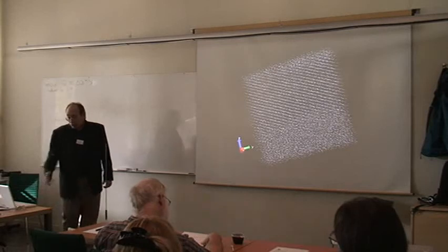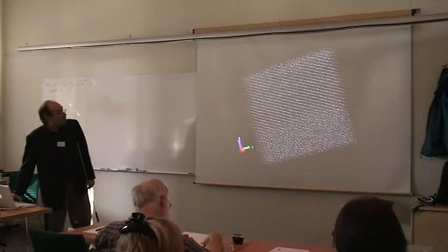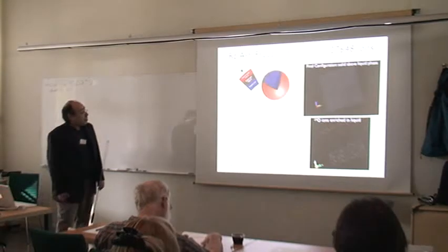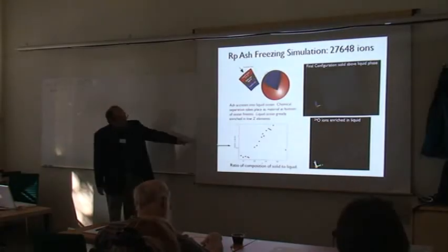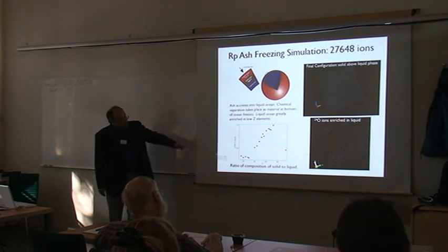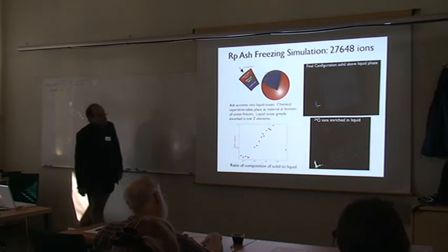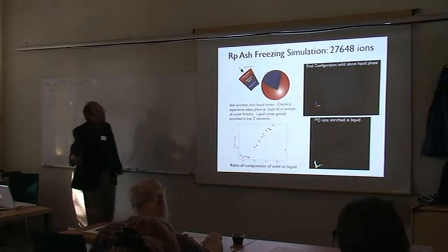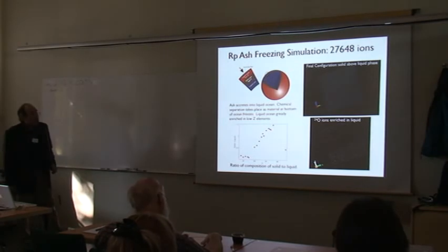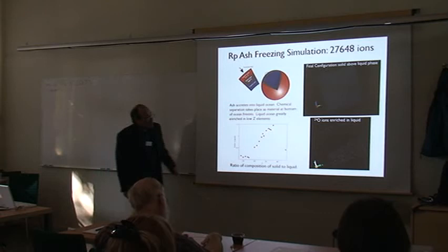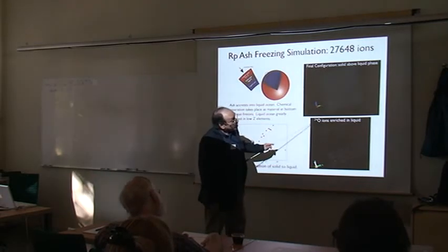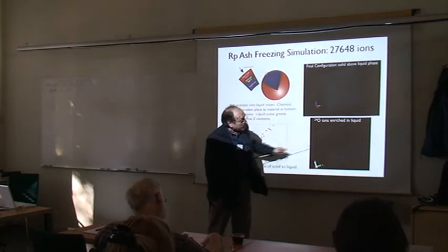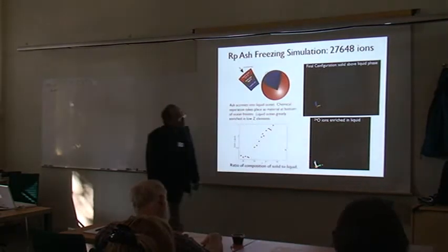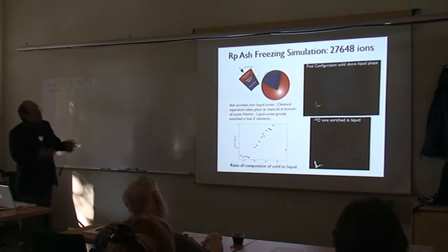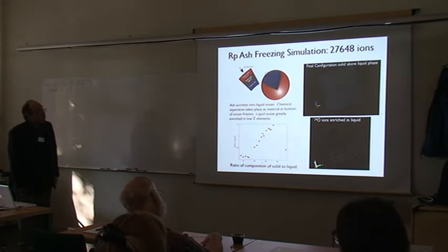You start with a mixture where the impurities are uniformly distributed between the solid and liquid, and just let it run for a while, and you find chemical separation. Here's the ratio of the composition in the solid to that in the liquid. For low-Z material like oxygen, that ratio can be 10%, so the liquid is enhanced in low-Z materials by a factor of 10 compared to the solid. Here's where the oxygen ions are - there's little oxygen in the solid up here, all the oxygen likes to go down in the liquid. So you get this chemical separation as the material freezes.